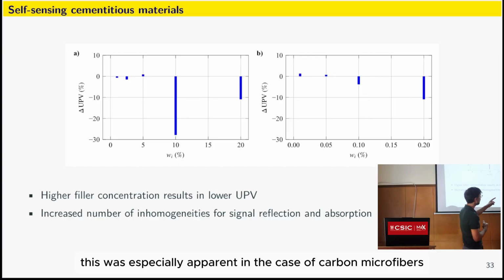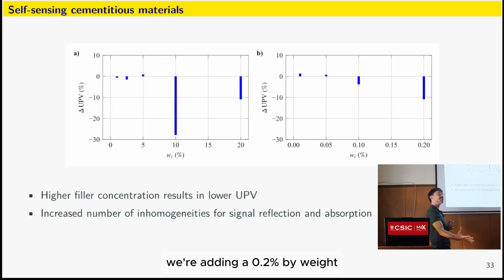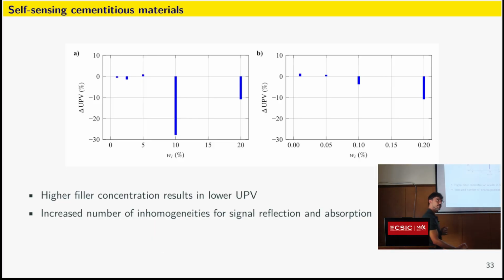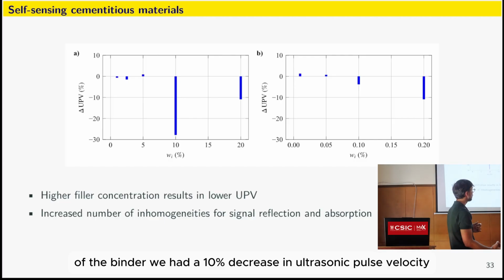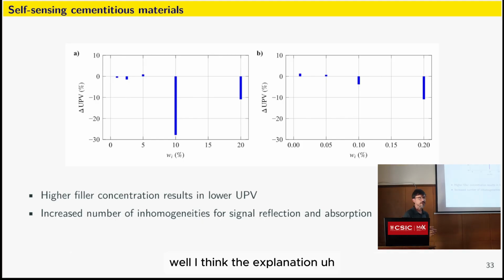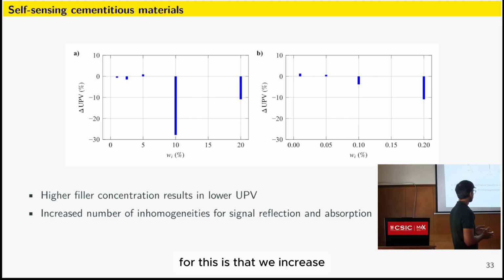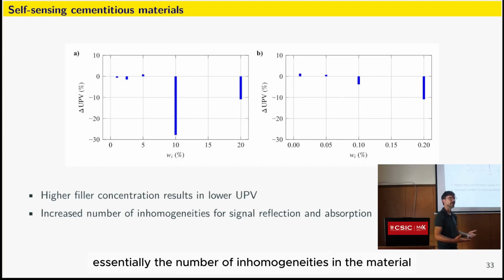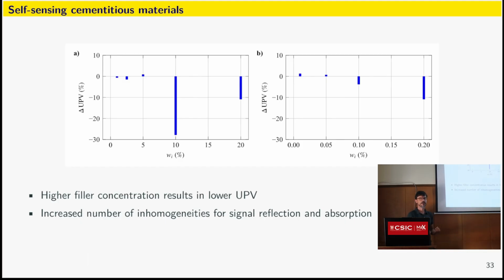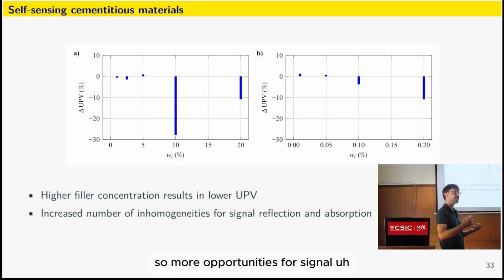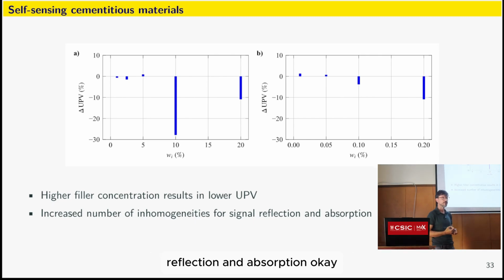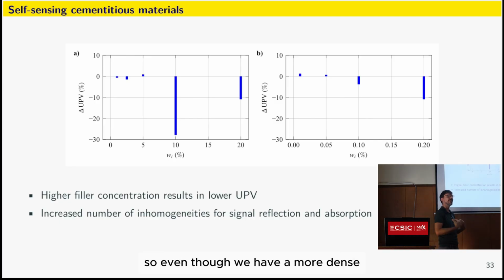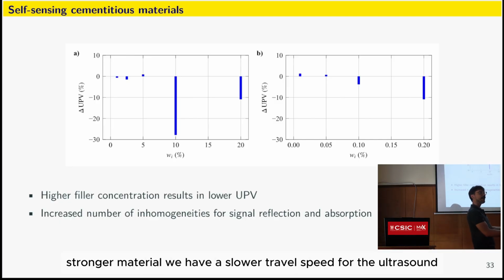This was especially apparent in the case of carbon microfibers, where adding 0.2% by weight of the binder, we had a 10% decrease in ultrasonic pulse velocity. I think the explanation for this is that we increase essentially the number of inhomogeneities in the material, so more opportunities for signal reflection and absorption. Okay, so even though we have a more dense, stronger material, we have a slower travel speed for the ultrasonic pulse.